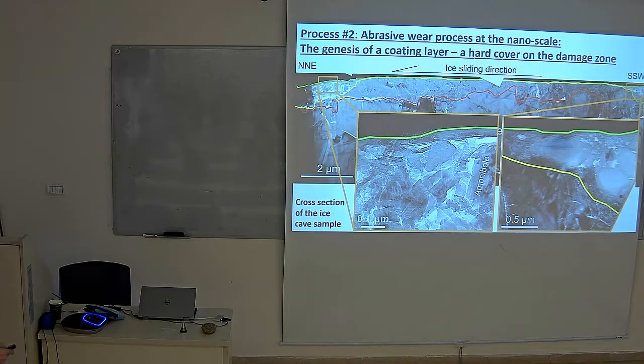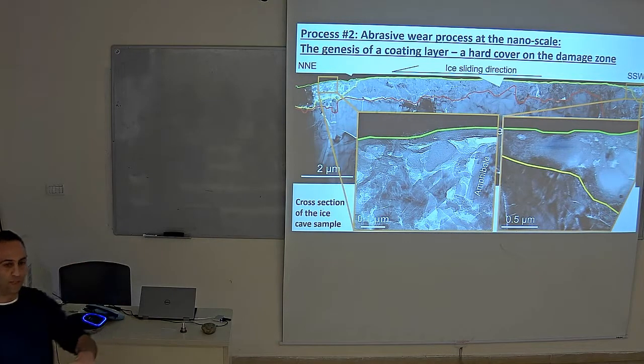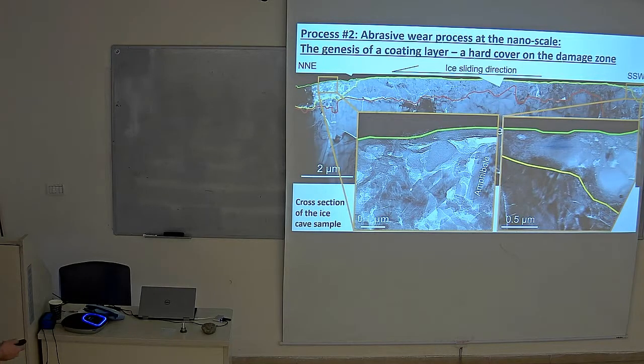By the way, all these are coated by a thin layer, tens of nanometers, of amorphous material coating that makes this material, this breccia, remain in the same place and not escape while I'm washing the sample before, when I'm preparing it, and so on.